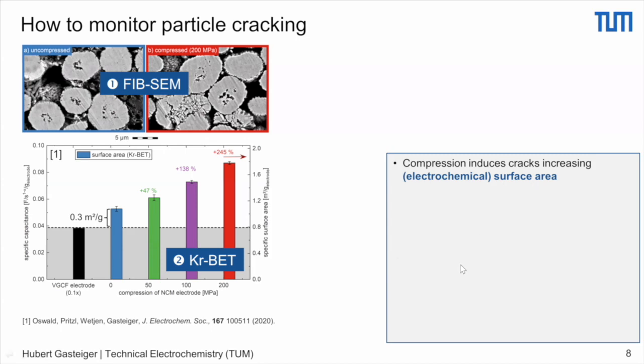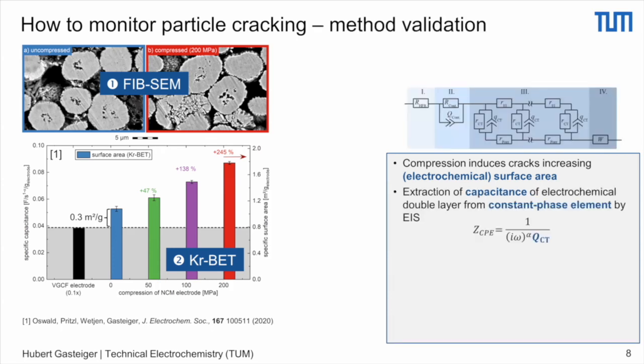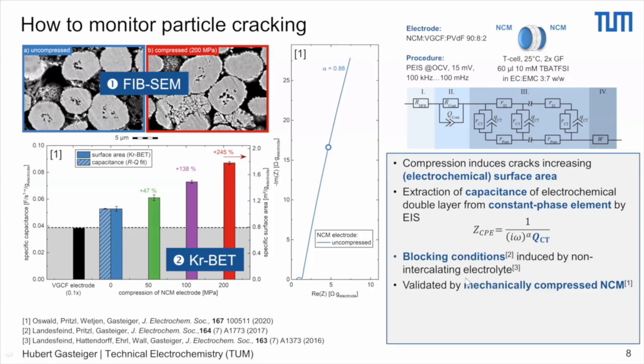And so we use this to actually calibrate our new method, which was trying to extract the capacitance of the cathode electrode using a transmission line model with constant phase elements. And when we do this, we utilize so-called blocking conditions. And so blocking conditions can be obtained by either using a non-intercalating electrolyte, which was done in this example here, or by going into conditions where the charge transfer resistance becomes very, very large. And so the typical impedance spectrum of blocking conditions is essentially more or less a vertical line, not quite vertical.